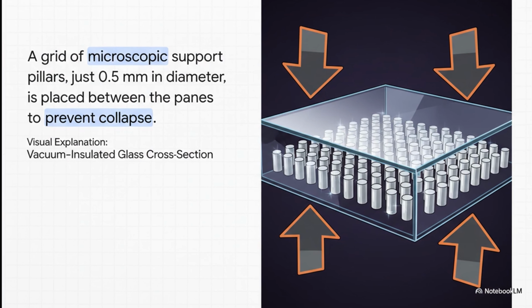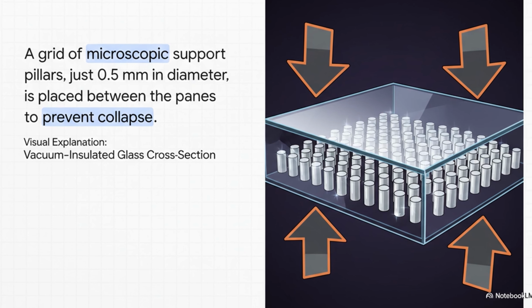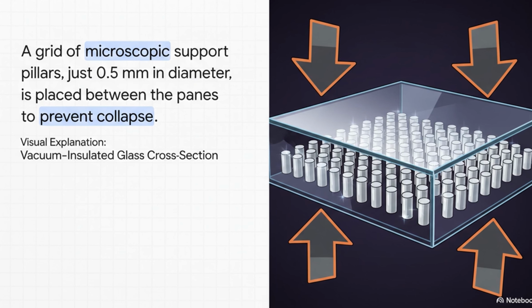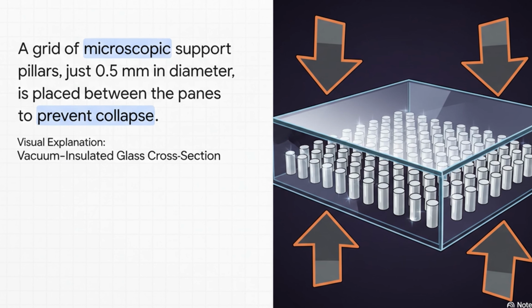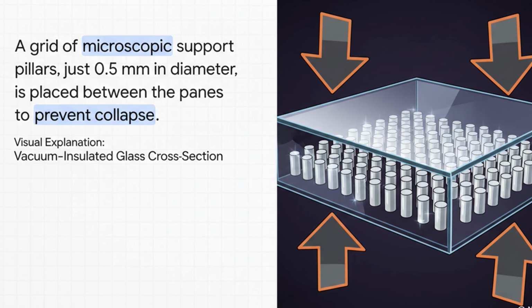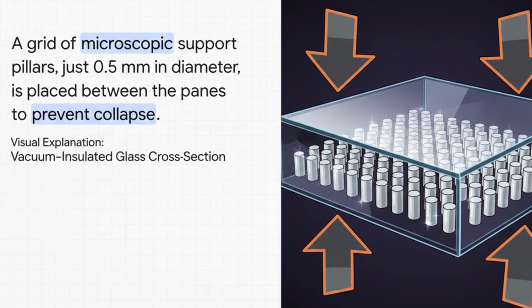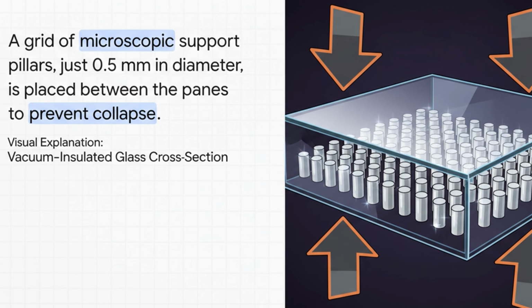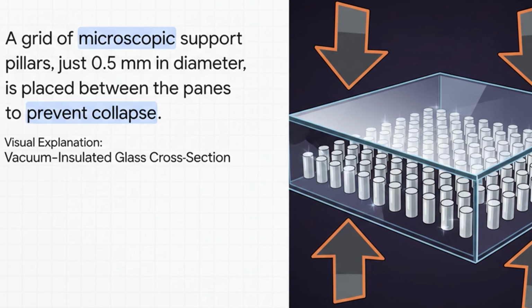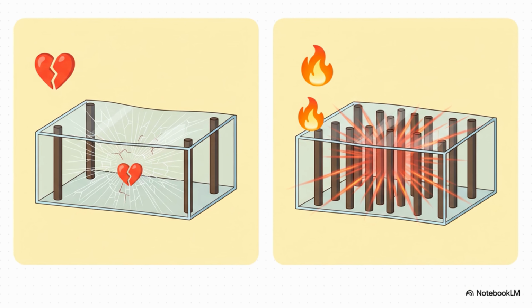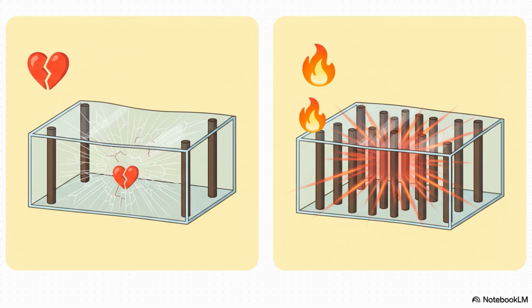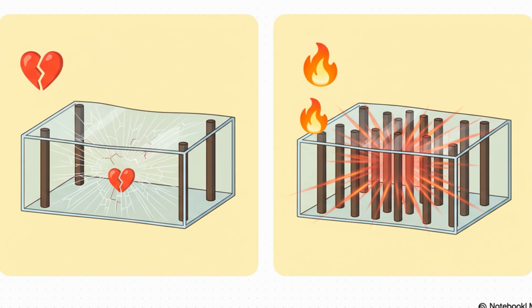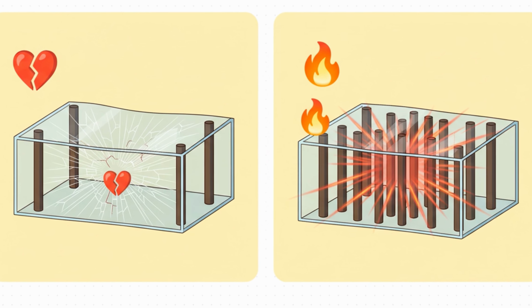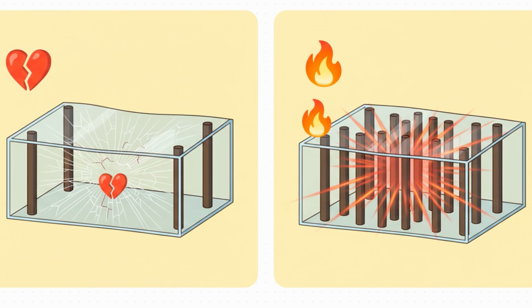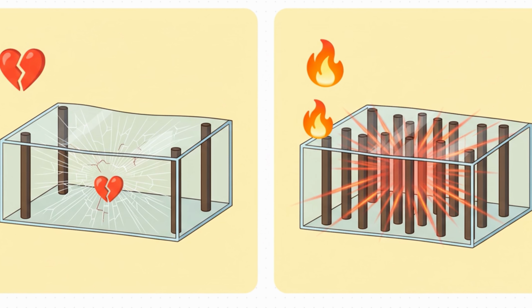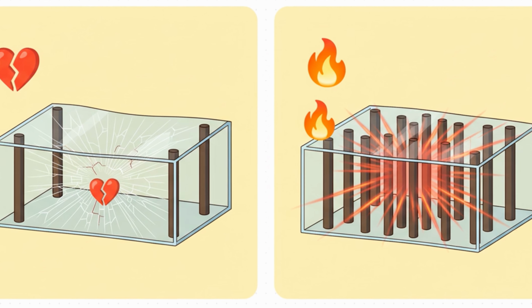The solution is just so elegant, and it's almost invisible. Engineers place this tiny grid of microscopic support pillars right there in the vacuum between the two panes. And these pillars, they're made of high-strength steel or ceramic. They're only about 0.5 millimeter wide, but they are strong enough to hold that glass apart against all that crushing force. But placing these pillars is this incredibly complex puzzle. It's a huge optimization problem. If you put them too far apart, the glass is going to bend inward and break. But if you put them too close together, the pillars themselves start conducting heat, acting like these tiny little thermal bridges that completely defeat the whole purpose of the vacuum in the first place. It's an incredibly delicate balancing act.